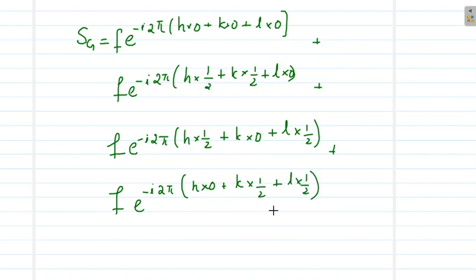So this is the effective structure factor. So you can see the 2 will cancel out in all the terms, and finally you will have Sg equal to f into, the first term is e raised to 0, which is simply 1, plus in the second term you have e raised to minus i pi into (h plus k).